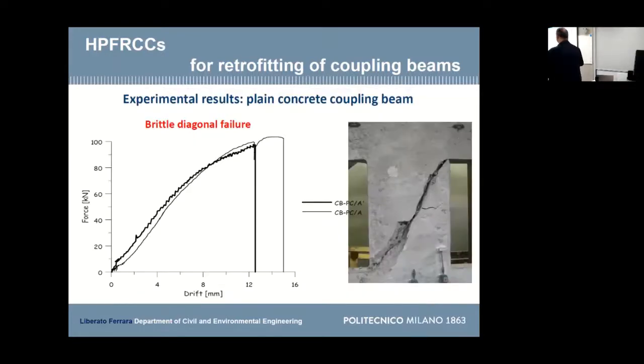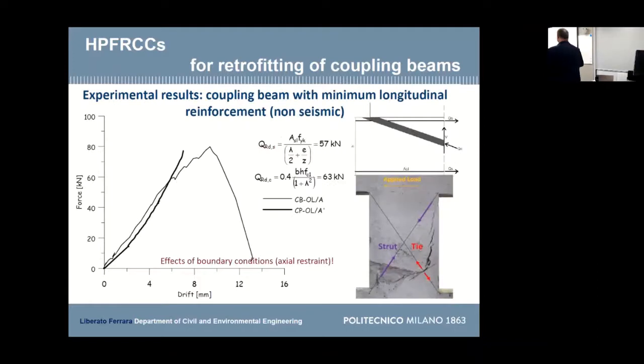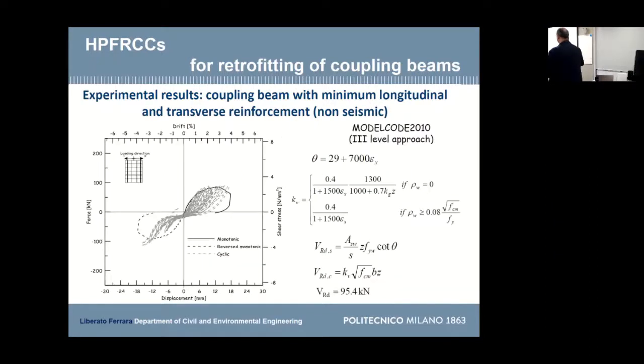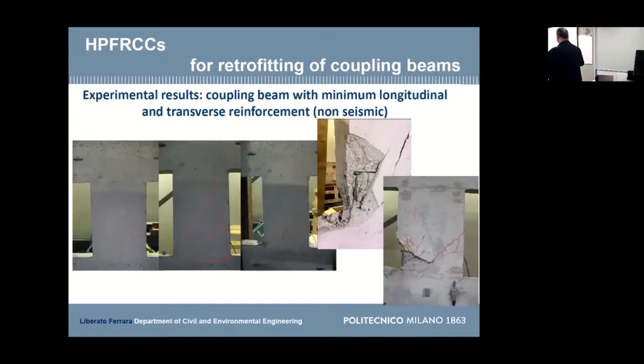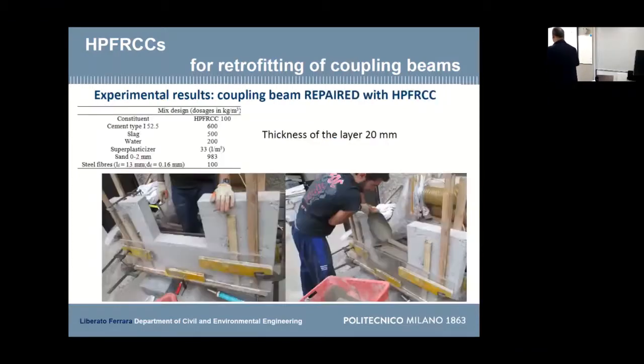And we tested, this was a beam without any reinforcement, shear diagonal crack. Theory is perfectly respected. Then we put longitudinal reinforcement with a strut and tie mechanism. And then we put our material, and this was the envelope, the monotonic curve, and these were the cyclic tests that were performed. This was the failure mode. You see, this was a typical failure mode of a compression strut, which fails. So we went into retrofitting.